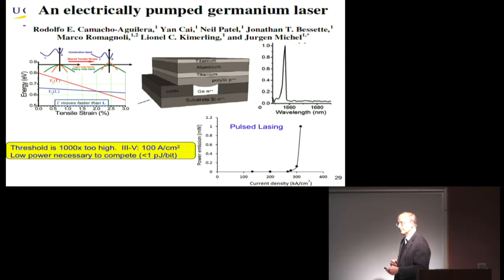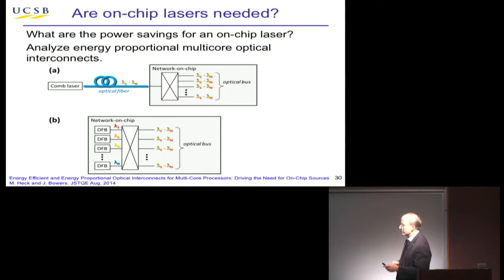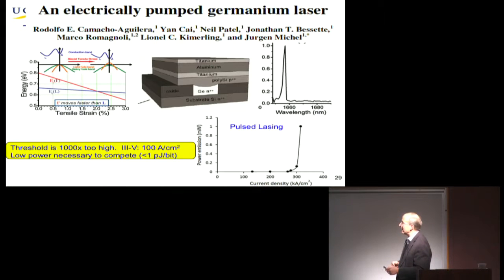So for the 3.5 watts, what's the data rate? Say 100 gigabit transceiver. So it could either be a 4 by 25 PSM4 in parallel, or it could be 4 wavelengths. And I'll show some examples of both. So my comment there is just that germanium detectors and modulators work really well. Germanium lasers don't work until you get to the point that it's direct bandgap.